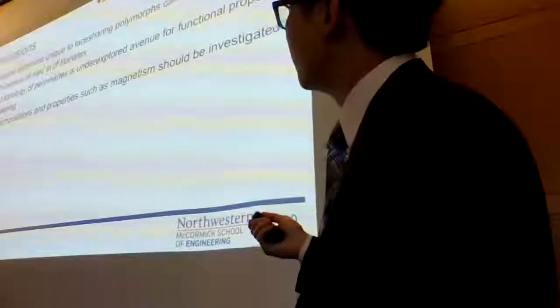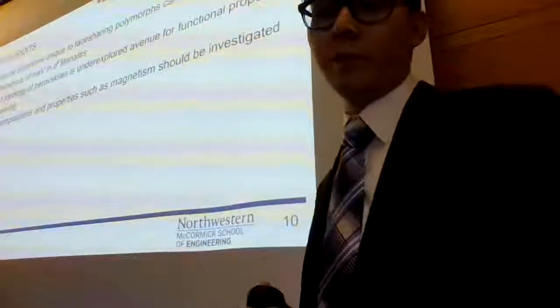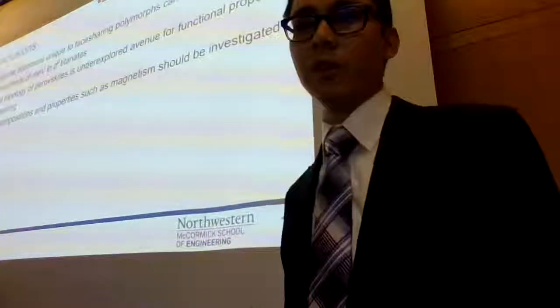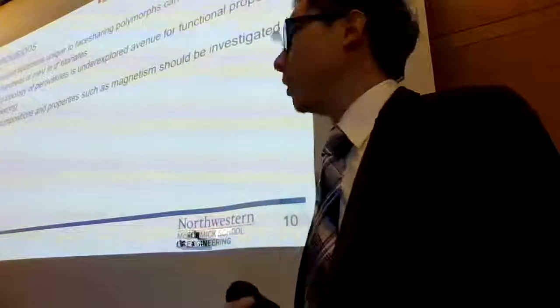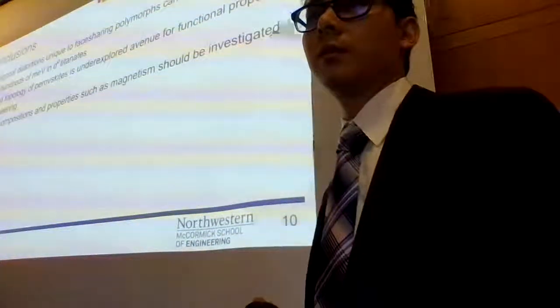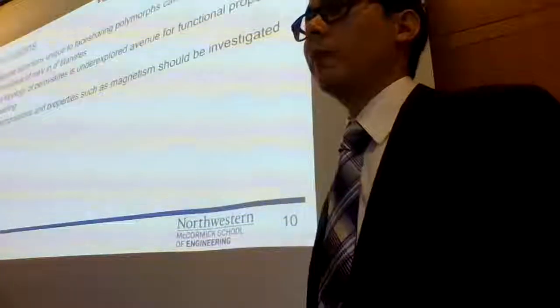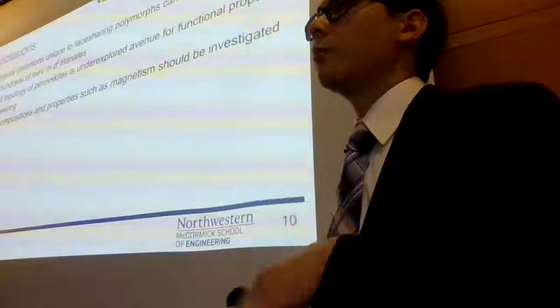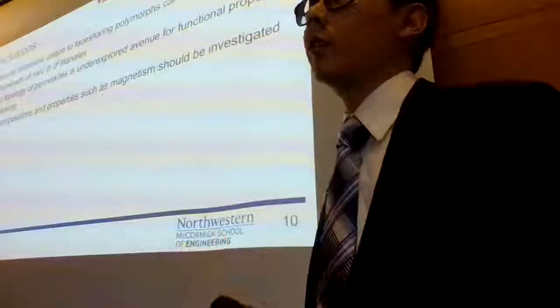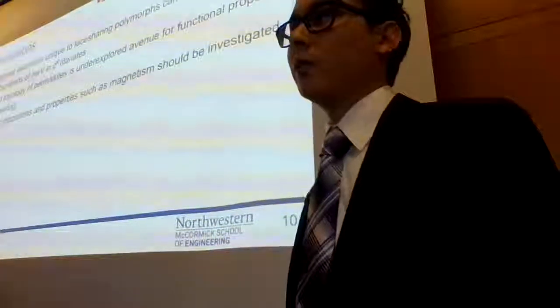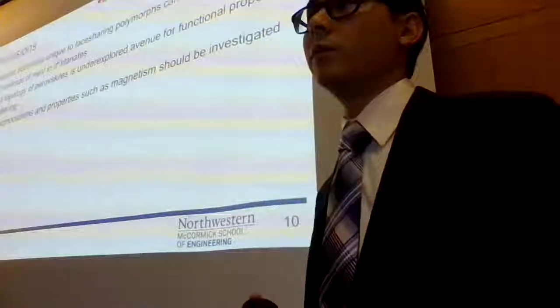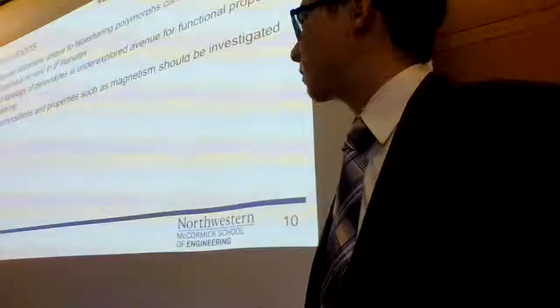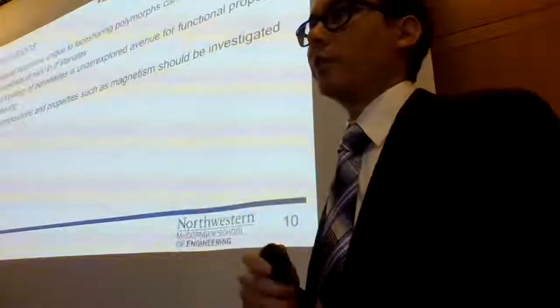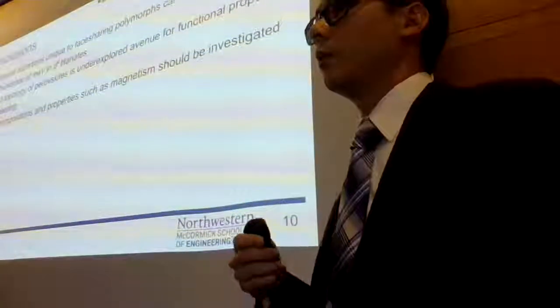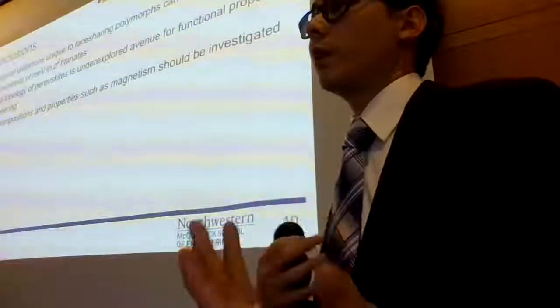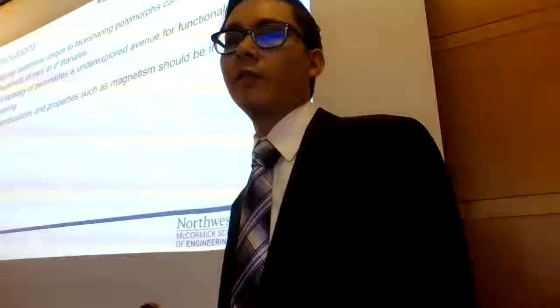So just to conclude from this section, these trigonal distortions, unique to phase-sharing polymorphs, can achieve band gap changes in the hundreds of meV in D0 titanates, which is an interesting phenomenon. I would say overall, the bond topology changing of these compositions is something that is really underexplored. In fact, when it has been explored, it's often been as a competing polymorph for, say, ion conduction in solid oxide fuel cells. So it's been viewed as a detriment historically. But there are so many compositions that might be amenable to being found in these polymorphs with advanced synthesis techniques. I think they're worth looking into. And there are additional properties that I didn't have time to get into here, but potentially having multiple cations stacked along those chains, you could think about creating interesting magnetic orders that you might not find in the normal perovskite variants, which would be interesting to see.